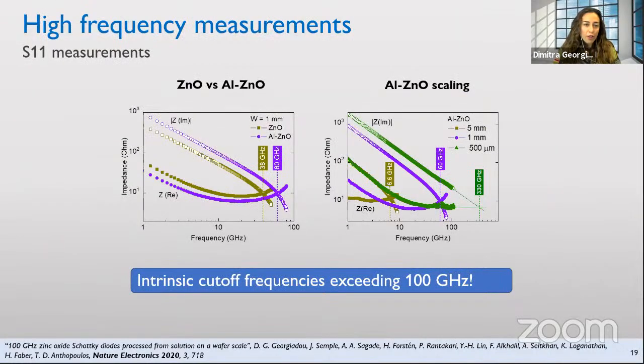So here are results with the high frequency measurements, which we got by de-embedding the S11 single port measurements we obtained with a vector network analyzer. The intrinsic cutoff frequency in this case is defined by the intersect of the imaginary and real part of the impedance, and it signifies the highest frequency at which signals can propagate. Basically, it refers to the intrinsic speed of the diode as defined by the junction resistance, the junction capacitance, and the series resistance values. In this case, we neglect any transmission losses, any load resistance, and impedance matching losses, which are usually present in actual rectifier circuits. That's why this is, as I said before, the highest value we can actually get.